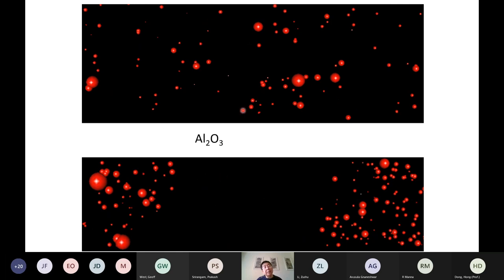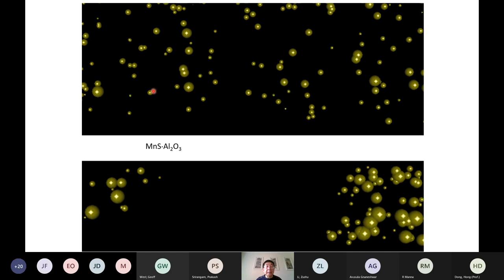If we look at the aluminum oxide, without electropulsing you see that they are distributed homogeneously in space, and after electropulsing, we cannot see any. There might be some, but this SEM machine can only detect inclusions larger than 0.7 micrometer; smaller than that we can't see. So here we can't see, which means in this area the inclusions must be less than 0.7 micrometer. This is without current pulse, and with current pulse is here. So the central part is very clean.